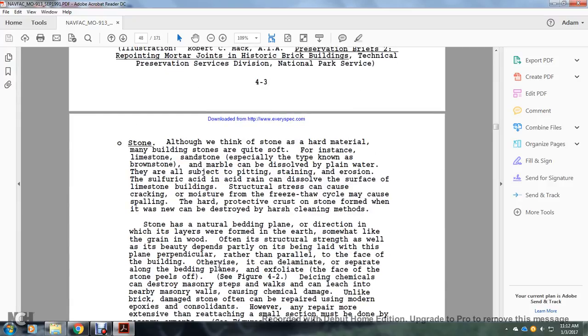All right, stone. Although we think of stone as a hard material, many building stones are quite soft. For instance, limestone, sandstone, especially the types known as brownstone, and marble can be dissolved by plain water. They are all subject to pitting, staining, and erosion. Sulfuric acid in acid rain can dissolve the surface of limestone. Building structural stress can also cause cracking. Moisture and the freeze-thaw cycle may also cause spalling. The hard protective crust on the stone can be destroyed with a harsh cleaning method.